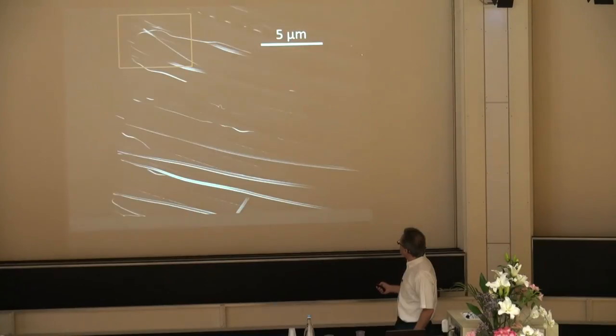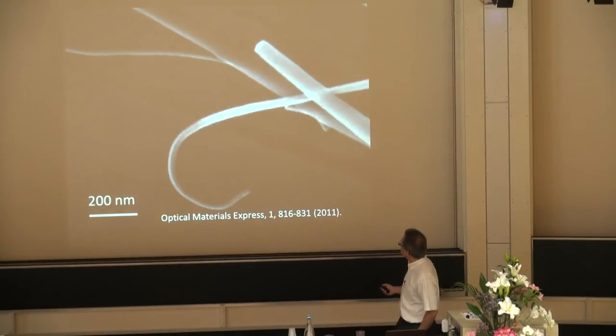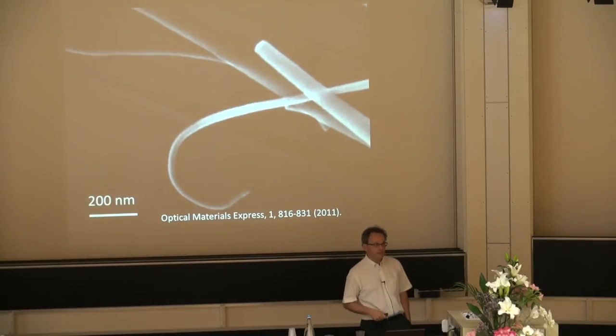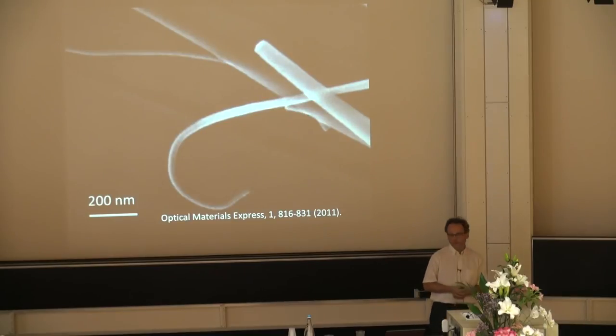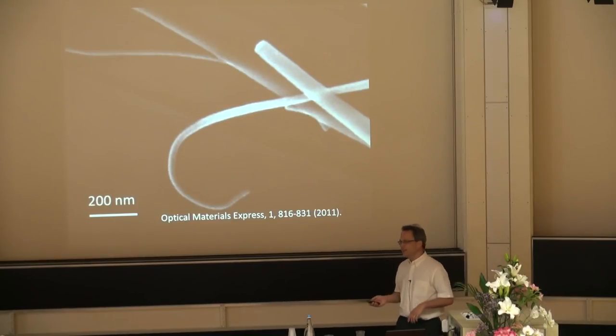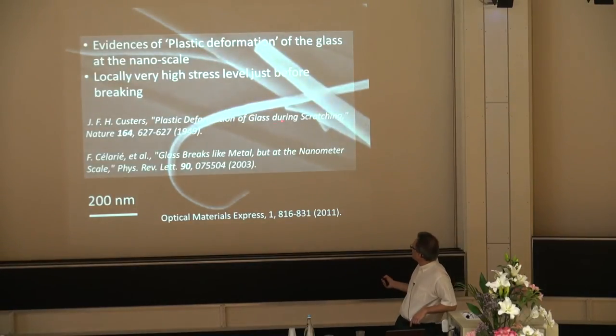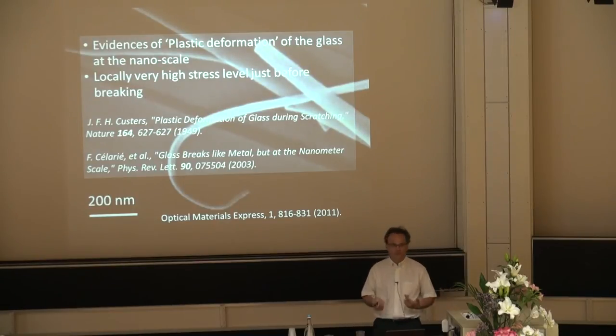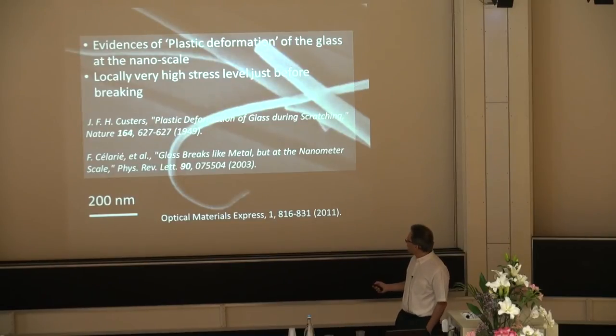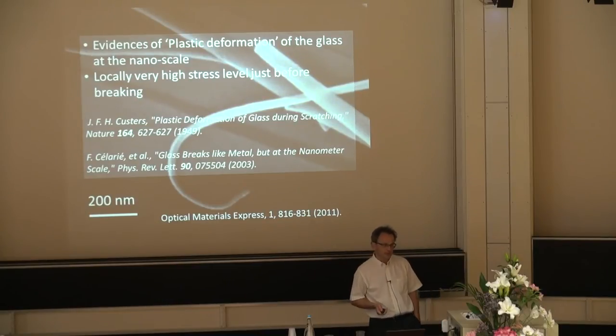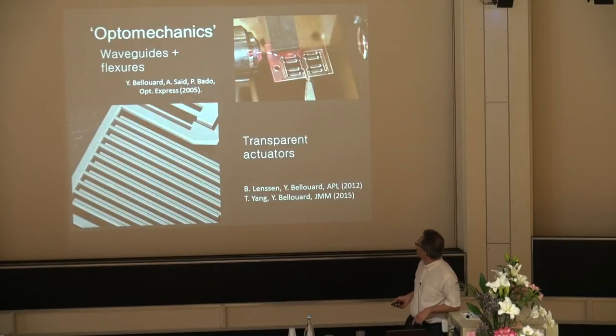But interesting, when you magnify and look at certain parts of the fracture, you find this kind of spaghettis and things like that, which shows that the glass has turned into a plastic deformation. So that's an interesting thing, is that glass at the nanoscale, in fact, deforms plastically, not anymore really a brittle fracture. And there are things that have been observed before, like you see very early on, actually. But if you do some scratching, you observe some kind of flakes. And it's a topic that is quite well studied. People try to understand how glass is breaking at a nanoscale. So just to point out that there's a lot that we don't know, in fact, and that's still worth exploring more. Okay, now what can we do?